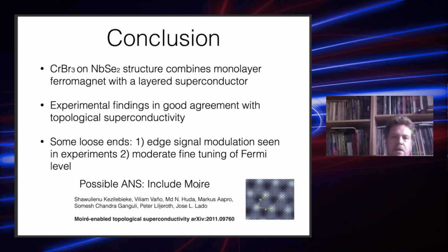And in the follow-up work of Peter Liljeroth's group, where I'm no longer a part of this collaboration, there is a possible answer to both of these issues. If you include also the Moire pattern that is very clearly seen in the experiments, that gives you, at least in the theoretical model, exactly the similar edge mode modulation that they are seeing in experiments.